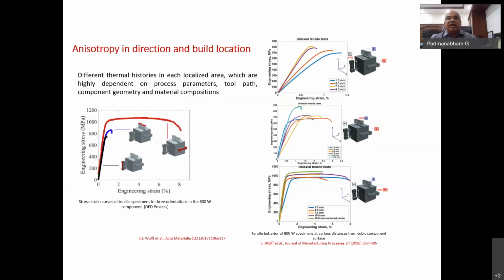So this is another. And then directionality issues, anisotropy I talked about. If you take specimens in 3 different directions as shown here, you can also see the stress strain curves of these 3 specimens. They are so different. The one which is taken in the XY plane is showing a nice ductility. You can see the strain, much larger strain compared to the specimens taken in other directions, right? And this is because of the nature in which you have built the component. In the vertical direction, you have layer by layer, and any small defect in those layers can result in what you can call delamination and failure.